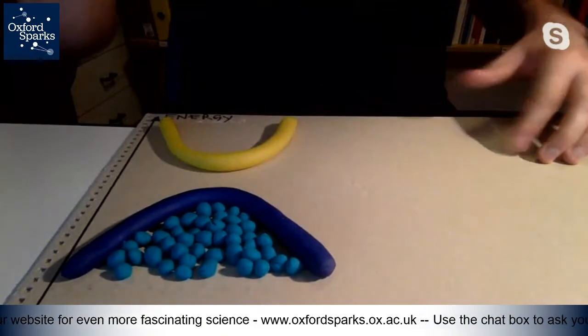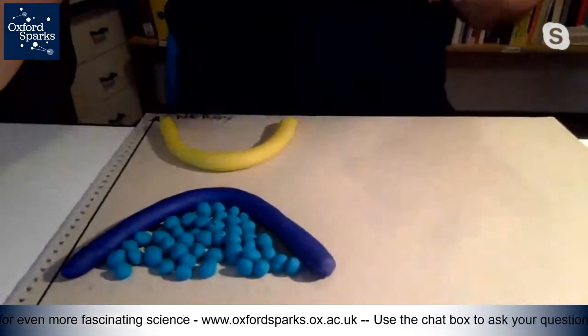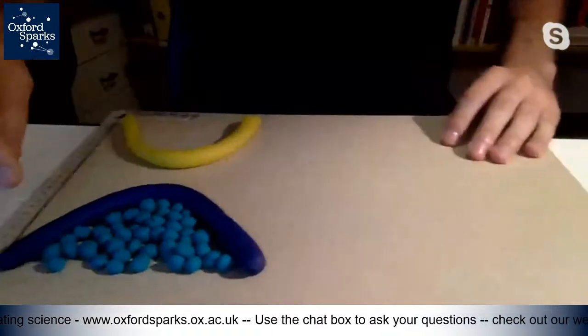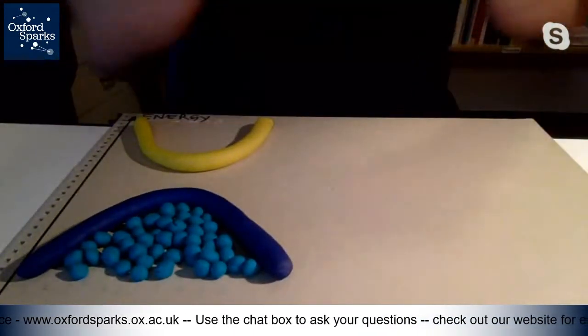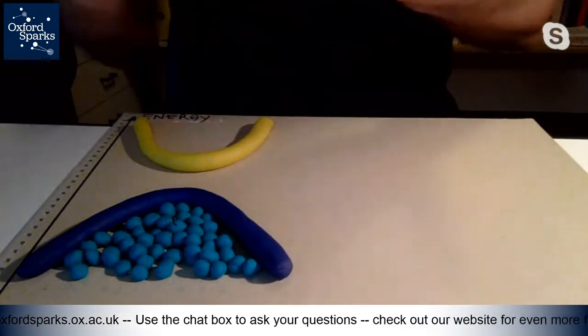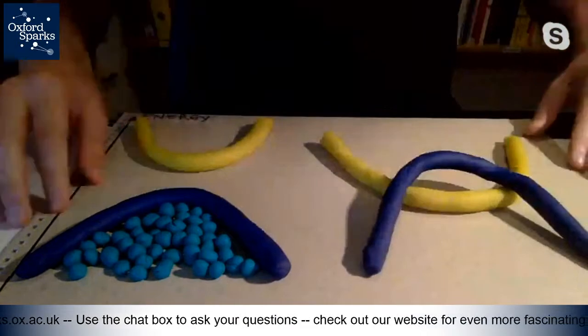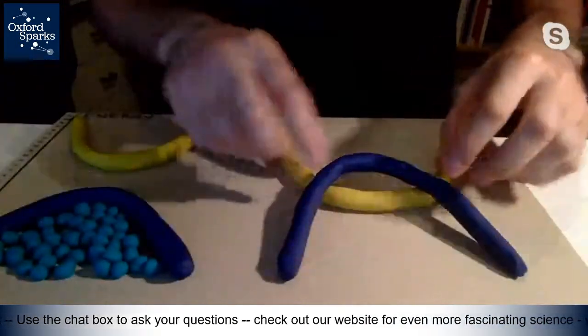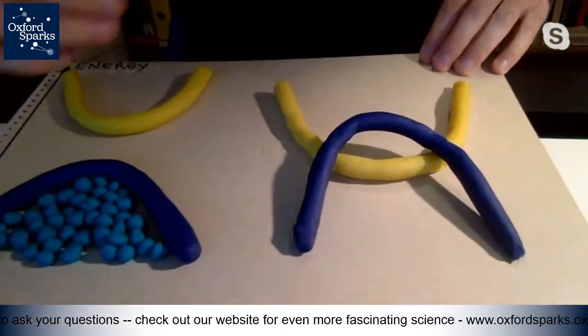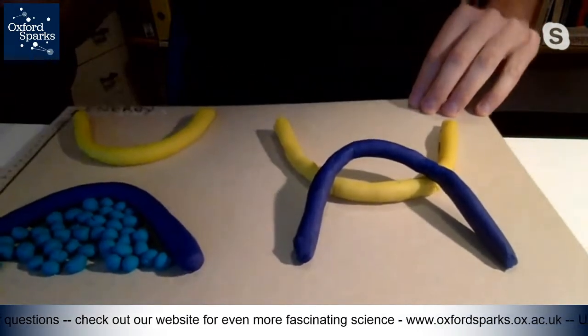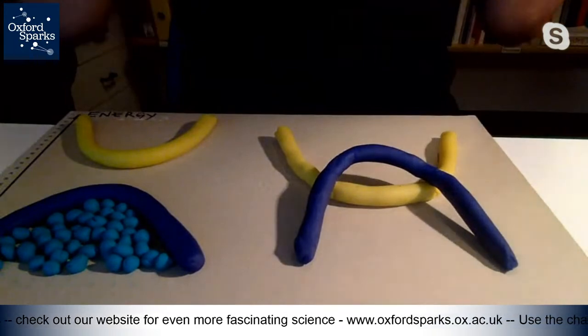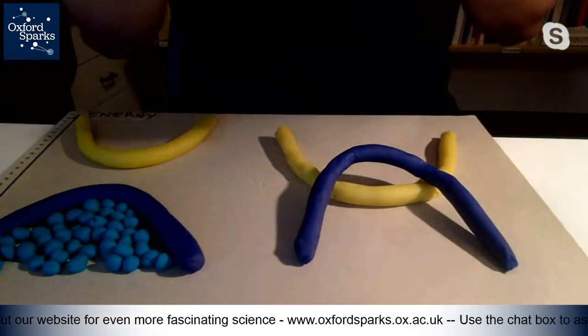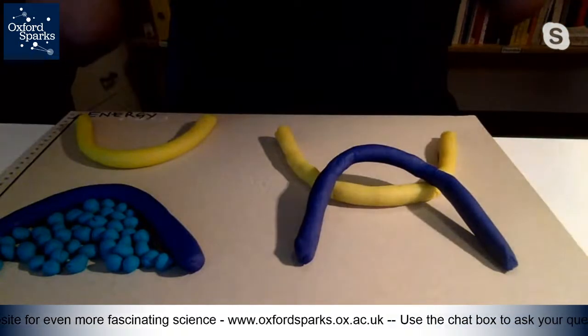Now, coming back to your question, what is a topological insulator or a topological material? So it turns out that these bands can also have a different topology, like the Möbius strip that I showed before, or like the teacups. They can have a different shape. And so if we compare it to the right side, we can have the situation where the bands cross like this. And this can be caused by what we call spin orbit coupling. So the spin of the electron, which is some sort of inherent magnetic moment that the electron has, interacts with its own orbital motion and makes these two bands overlap.